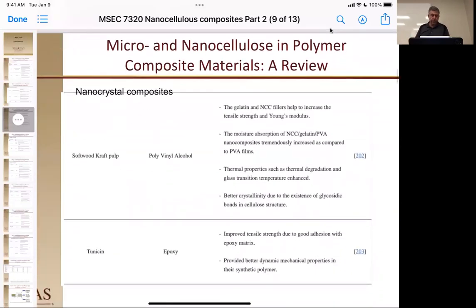So when we go to a kraft pulp, this is basically stuff like pine, fir. With polyvinyl alcohol, it had good strength, increased the thermal degradation in TGA, and better crystallinity because of the bonds between the sugars in the nano and the polyvinyl alcohol. I want to show you that the diversity of where you can get these nanocrystals is amazing. In epoxies, it improves tensile strength and has good adhesion, which is interesting, and it has better dynamic mechanical properties. So imagine you're getting your better tan delta.